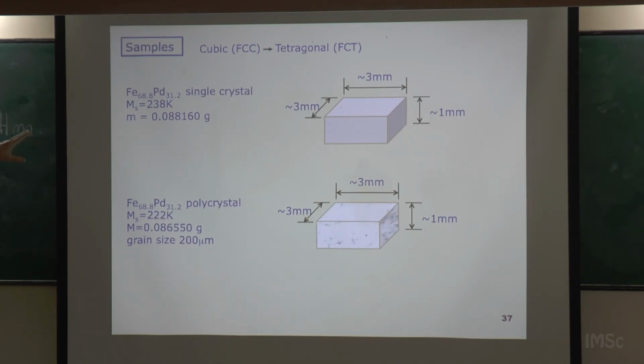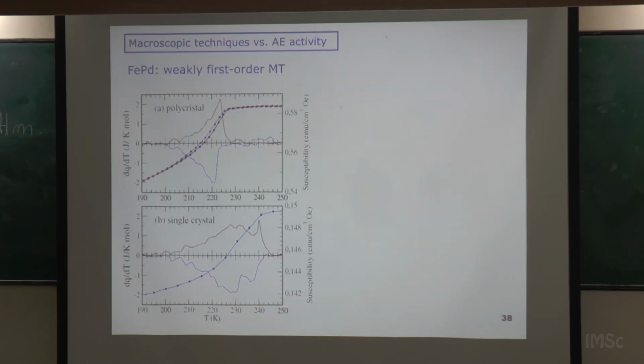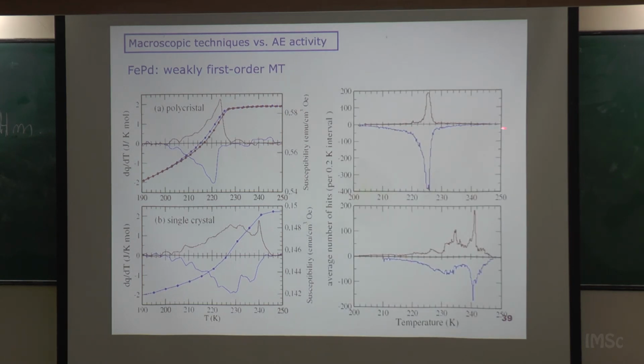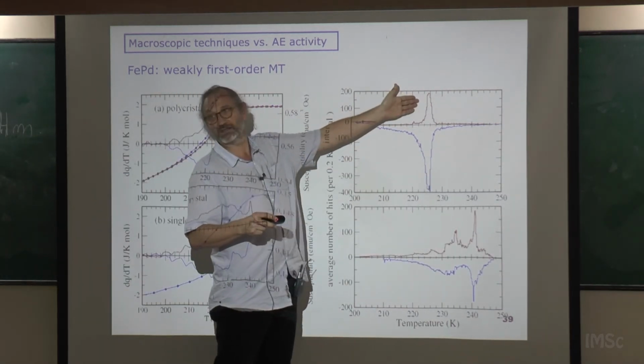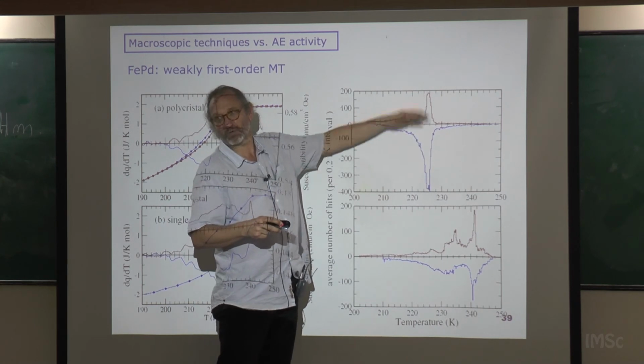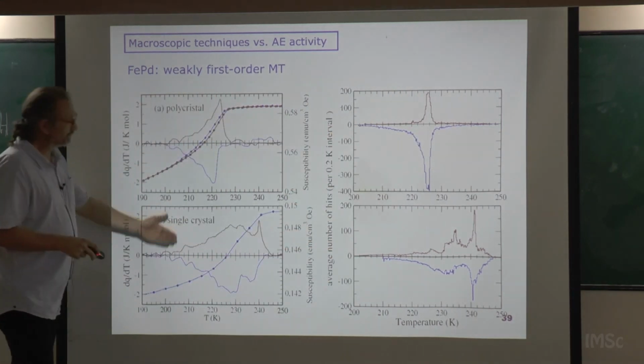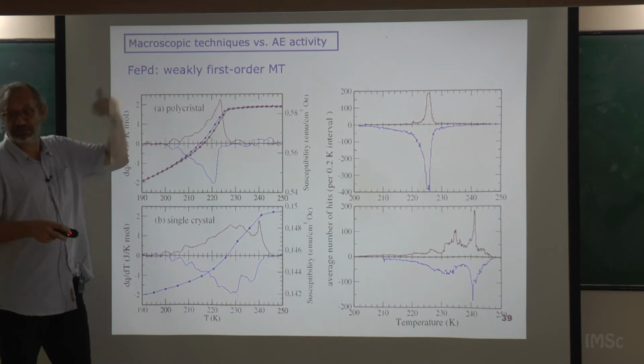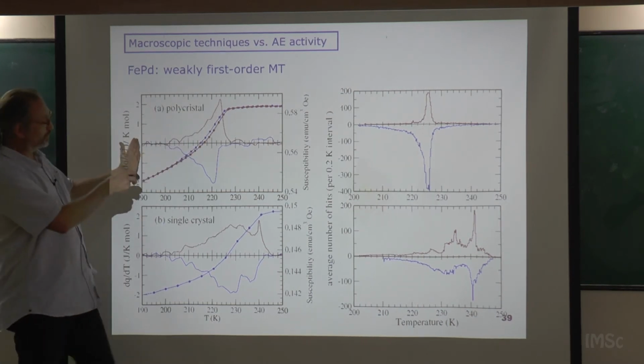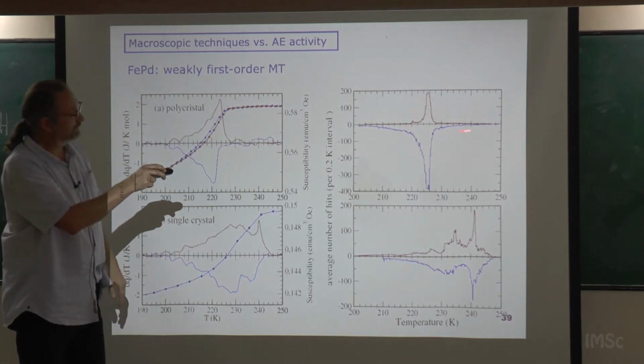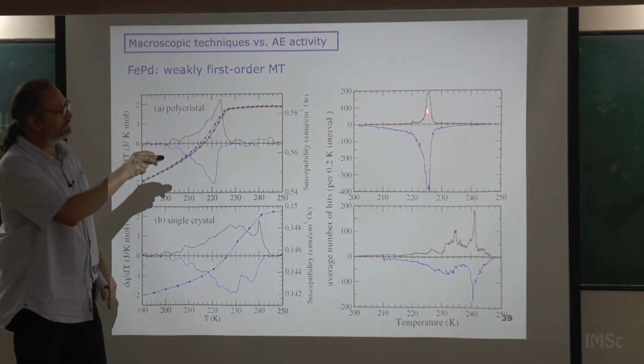This is iron palladium. Iron palladium has a cubic tetragonal phase transition, martensitic phase transition. We studied here a polycrystal and a single crystal. Just very fast, the message. This is calorimetry, but we go to the acoustic emission. So this is the single crystal. When you cool, it's plotted like this because I plot cooling and heating in the same curve, but of course the number is always positive. In calorimetry, it makes sense because latent heat changes sign, but then just to compare, I plot like this. When you cool, this is the activity. When you heat, this is the activity.